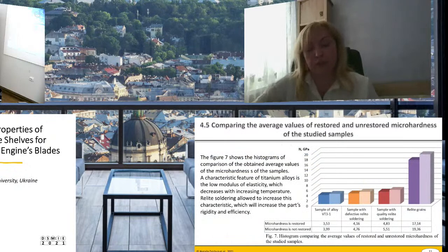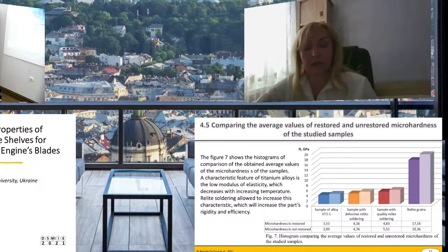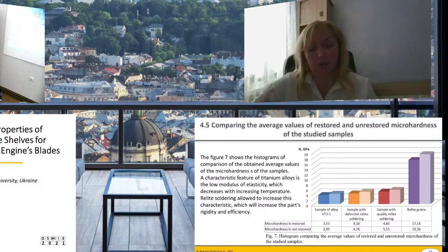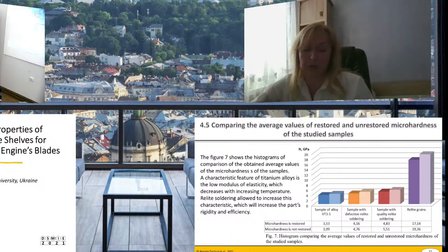Figure 7 shows the histograms of comparison of the obtained average values of the microhardness of the samples. A characteristic feature of titanium alloys is the low modulus of elasticity, which decreases with increasing temperature. Solder allows increasing these characteristics, which will increase the part's rigidity and efficiency. The minimum mechanical properties, namely the tensile strength, Young's modulus, and ductility index, are given in table 7 on the next slide.